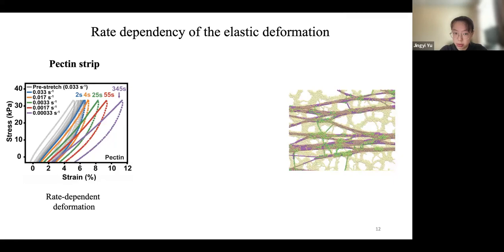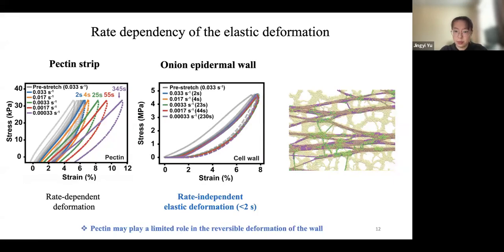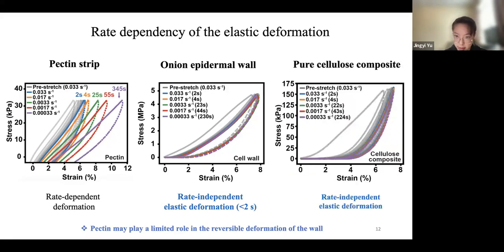However, when we repeat the experiment on the onion epidermal wall, we see that when we change the strain rate by 100-fold, the stress-strain curves basically overlap on top of each other, suggesting that the elastic deformation of the wall actually remains rate independent. By comparing these two graphs, it shows that the viscous flow of the pectin may play a very limited role in the overall elastic deformation of the cell wall. And in order to test if this rate-independent elastic deformation is a typical behavior of cellulose-like material, we also repeated this test on the pure cellulose composite, and we can see that indeed the cellulose composite also shows this rate-independent elastic deformation.